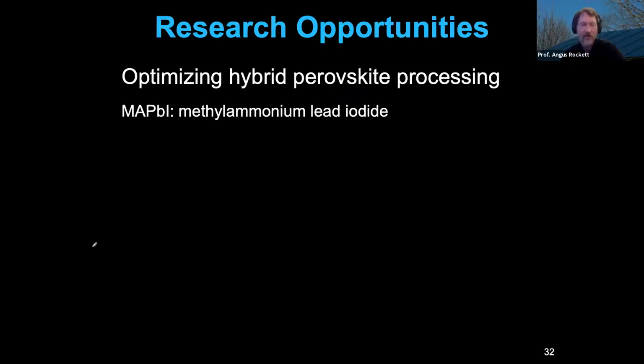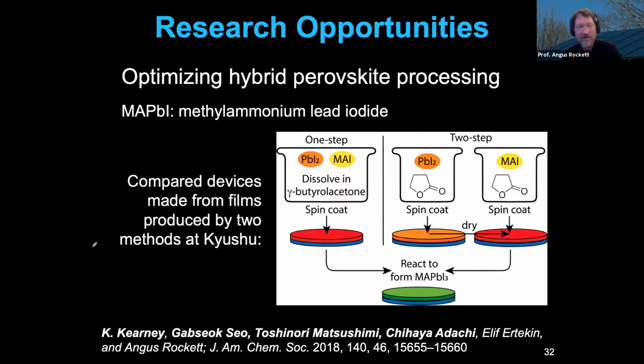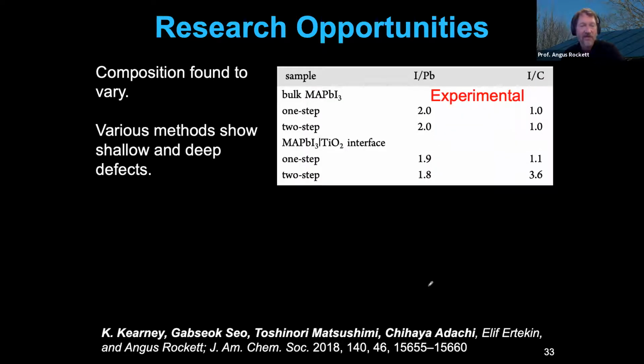There's also a study that we did in collaboration with Professor Adachi at Kyushu University. And so this is with methylammonium lead iodide, a similar material. And the group at Kyushu did two different deposition processes, a one-step process and a two-step process, spin coating onto a substrate and then reacting to form this methylammonium lead iodide material. They characterized the material and looked at different compositions. It's also been studied and shown that there are some deep defects in the material that are a problem.